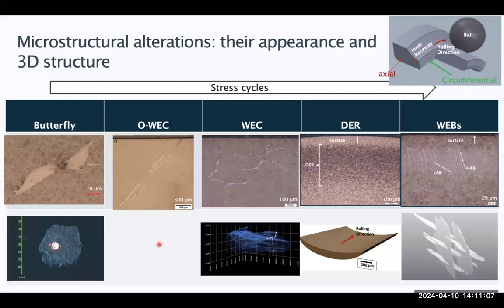Also recently we have found, this hasn't been published yet, but we are in the process of writing this up, that butterflies, although all the literature shows butterflies as having a center and two wings, and even some modeling has presented them in 3D as dumbbell shaped, actually look like a donut shape. In the center, you have the inclusion, and then you have the white areas surrounding it. Depending on which stage the butterfly was forming, you could have the whole inclusion encapsulated by the white area or not.